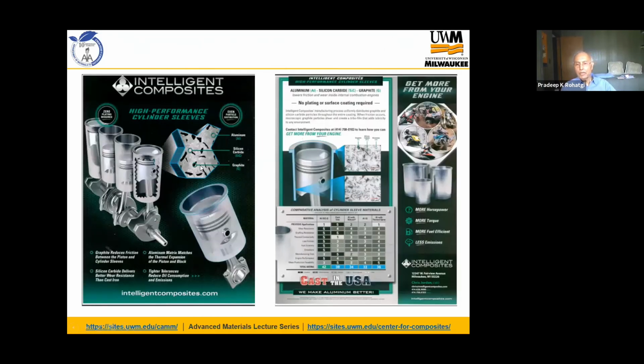In addition to adding one reinforcement like graphite or silicon carbide, there has been development of incorporating more than one reinforcement, and this is an example where graphite and silicon carbide, the black is graphite and fine silicon carbide is here, and this hybrid aluminum silicon carbide graphite has a better microstructure.